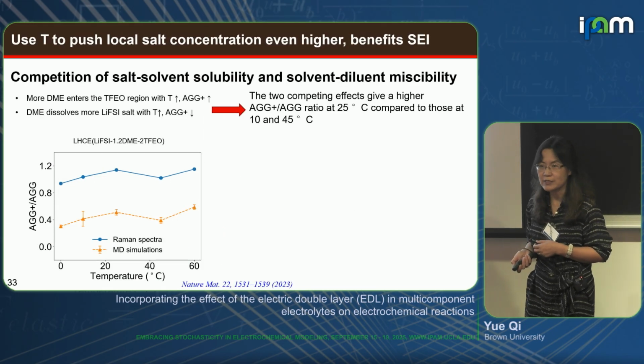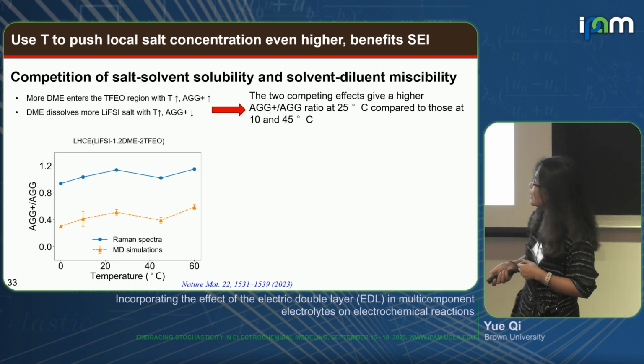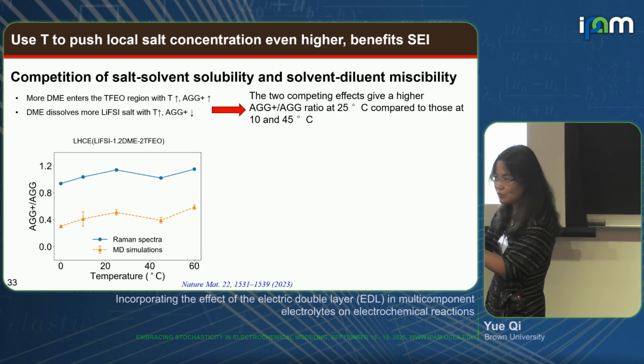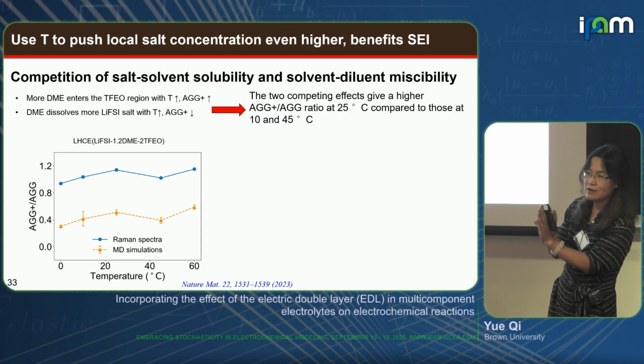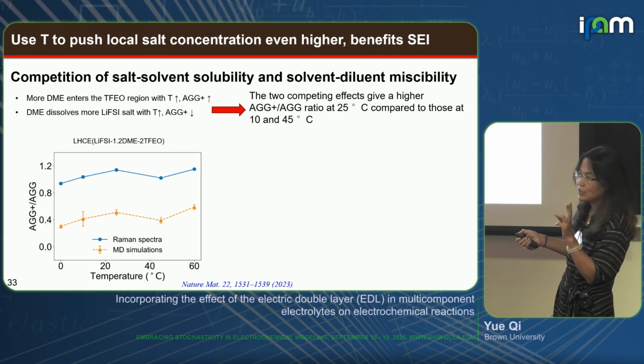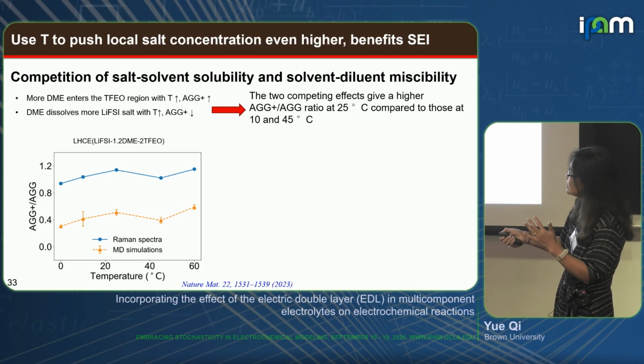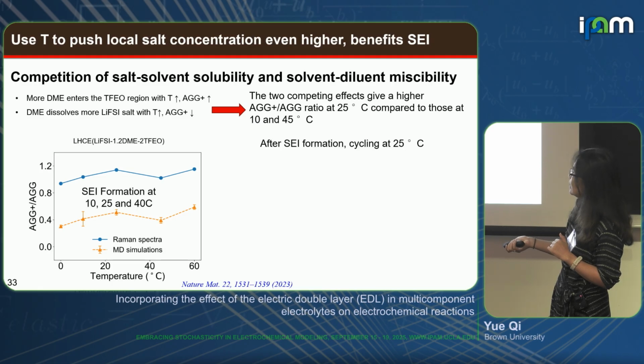And so we have to use this, right? If we have learned something, we have to make it useful. In this case, we make it useful by finding a temperature that forms the SEI with higher ion concentrations. Typically if you change the temperature, you solvate the ions more, right? So you would think that the aggregate concentration will decrease with an increase in temperature. But when this increases, I also told you this solvent can get into the TFEO diluent. So then we'll have fewer solvents available to solvate the salt. So that will lead to aggregates increasing. So you have a Goldilocks peak value right here. So we can use this peak value to form the SEI.